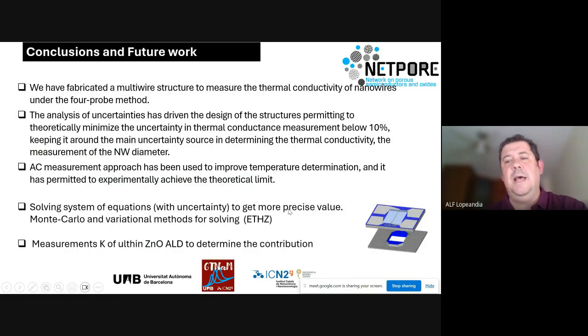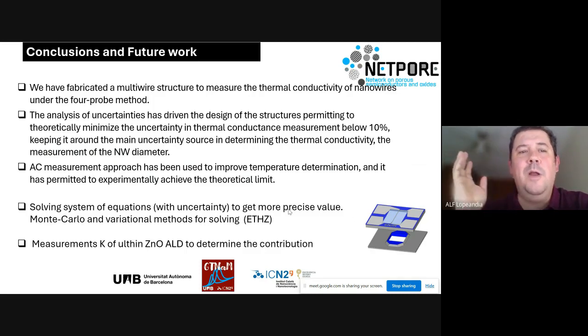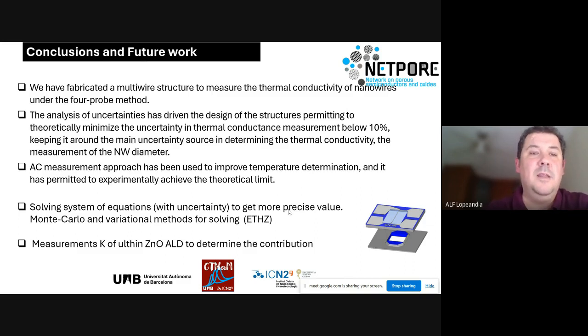And saying that, I can finish. I think I lasted a bit longer than 30 minutes, but I wanted to say that we were able to fabricate a multi-wire structure to measure the thermal conductivity of nanowires under the four-probe method. The analysis of the uncertainties has driven the design of the structures, permitting us to theoretically minimize the uncertainty of the thermal conductance measurements below 10%, keeping it around the uncertainty in determining the thermal conductivity, which is driven by the geometrical parameters, by the measurement of the diameter.